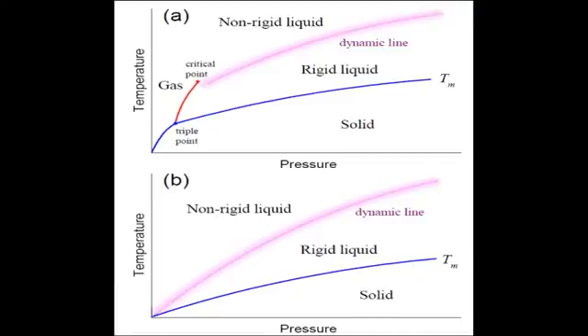The dynamical line, we call it Frenkel line, corresponds to the loss of shear stiffness of liquid at all frequencies. We remind that the ability of liquid to flow is associated with zero shear rigidity that distinguishes liquids from solids.